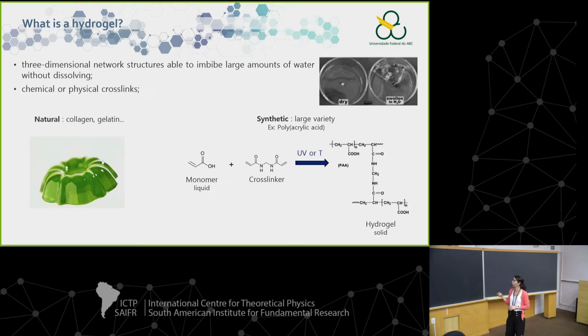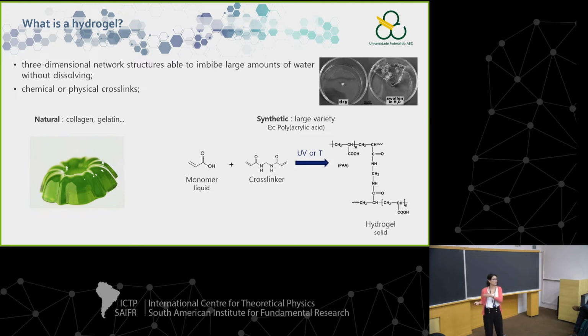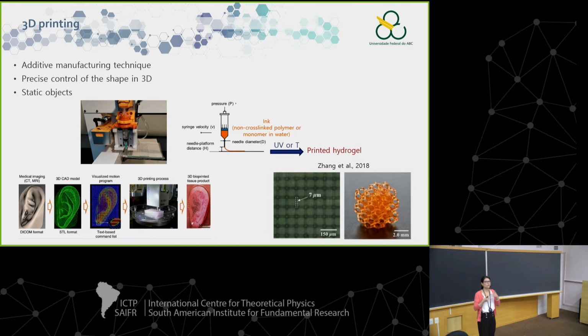Basically, we choose a monomer, which can be liquid or dissolved in water, and we transform it into large macromolecules, and we use a crosslinker, in that case a chemical agent, in order to crosslink these long polymeric chains. And to do this polymerization and crosslinking, we use energy, which can be UV light or temperature. In our case we are using UV. Here I show the polymerization of polyacrylic acid that I will use in the project I will show you. And 3D and 4D printing.